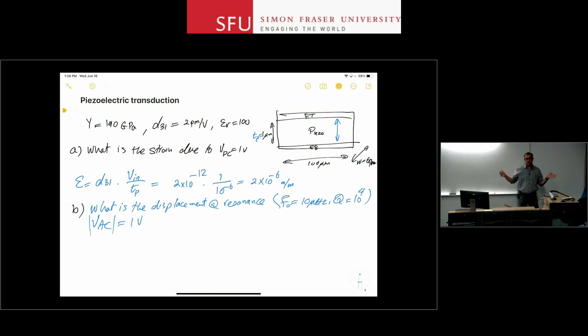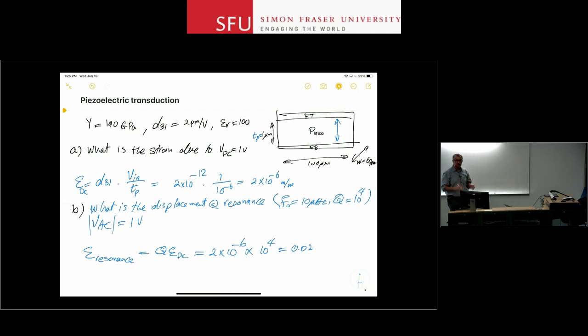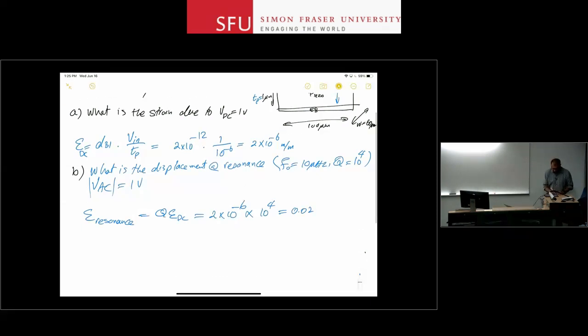But at resonance, everything is multiplied by Q. So the strain at resonance, let's say epsilon resonance, is going to be Q times epsilon DC. And this is my strain at DC. So quickly I can see that it's going to be 2 times 10 to the minus 6. Q is 10 to the 4 for this device. So this is going to be 0.02. That's 2% strain. That's actually a large amount of strain. Usually you shouldn't really get that much, but that's 2% strain. The relative change in length is 2%.